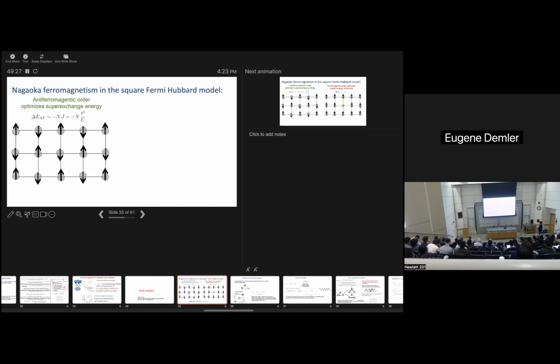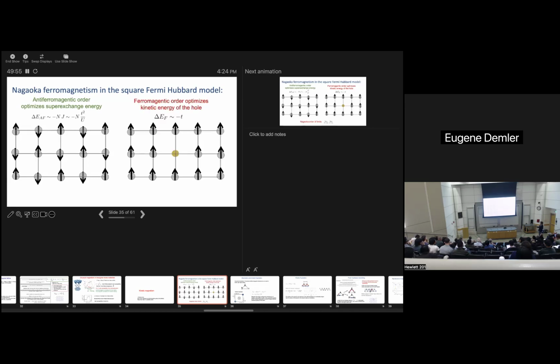actually the history of kinetic magnetism goes back to Nagaoka, and his argument was kind of curious, so let me take you through it. It was done in the context of the square lattice. So he said, well, okay, we just talked about antiferromagnetic interaction. If we have 1 fermion per site, spins align antiferromagnetically. Every pair of spins gains energy t squared over U, and there are N spins in the system. Now imagine that we put one hole, and we ask, what is the best background for the hole to propagate? It's best when all spins are aligned, because now, regardless of the different trajectories of how the hole moves, they all interfere constructively. So that really lowers the kinetic energy of the hole.